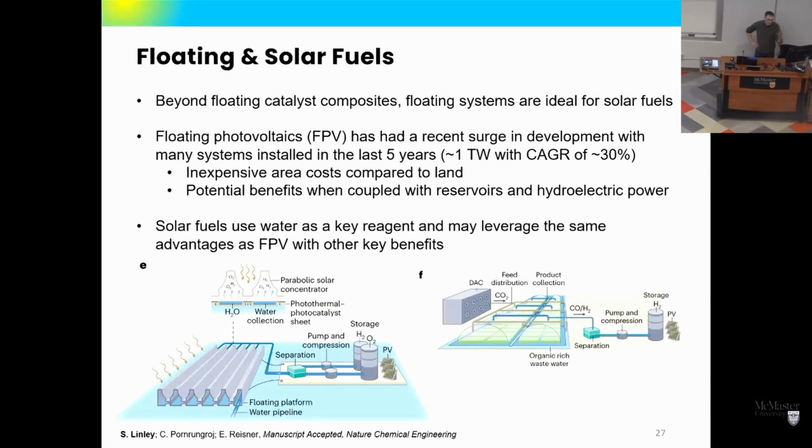Yeah, for sure. So obviously we want to increase the surface area of our catalyst. Also, when we're using those hollow glass microspheres, there is some ability to capture any light that initially passes through that material. We've got reflection within those systems. That is a nice system to work with. It's just the inherent fragile nature of the material, right? So we've got to try and balance that durability of the material and ability to capture and reuse it with its inherent ability to capture the